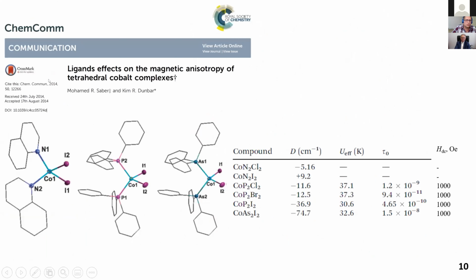One more work, also a tetrahedral complex of cobalt, where cobalt is surrounded by two halogen ligands and two donor ligands with nitrogen, phosphorus, and arsenic atoms. The calculation for that compound shows a significant decrease in D value with an increase in the electron donor properties of the ligand.